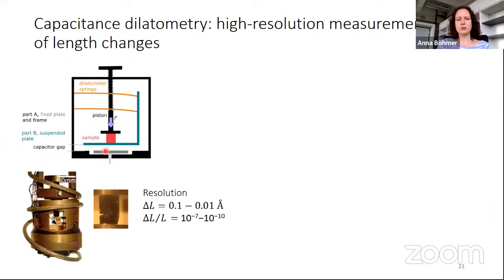And if you do that, all you need to do is read out the capacitance to get the length change of the sample. And we can do that with very high resolution. We can see length changes of fractions of an angstrom.